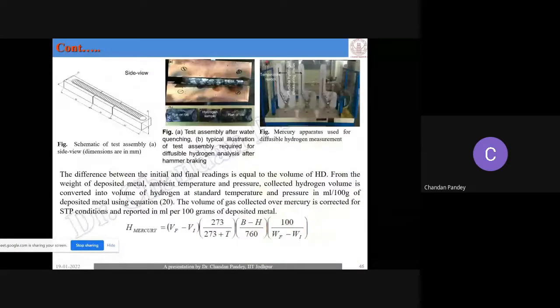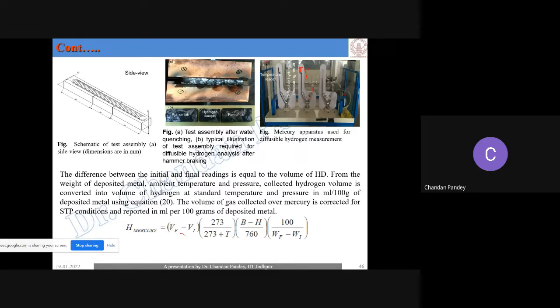So after capturing the hydrogen at a low temperature, we put the sample into the mercury solution. This is the mercury or glycerin solution, depending upon which process we are going to use. We put the center piece here, and when the sample comes to room temperature, the diffusible hydrogen comes out of the sample and displaces the mercury. We measure the displacement, and with the help of that displacement, using a formula, we can measure the diffusible hydrogen content.